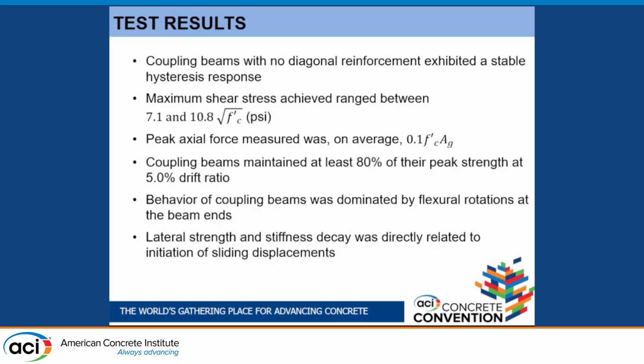We got at least 5% drift ratio before we got 20% strength decay. The behavior was dominated by flexure until the very end, where for the case of the U-dowels, the coupling beam started having quite a bit of sliding at this section at the end of the U-dowels.